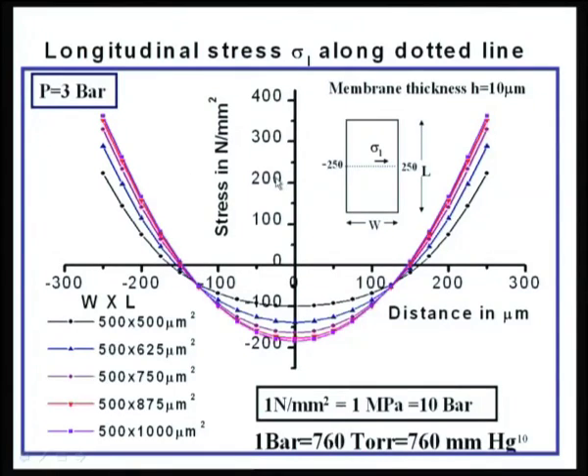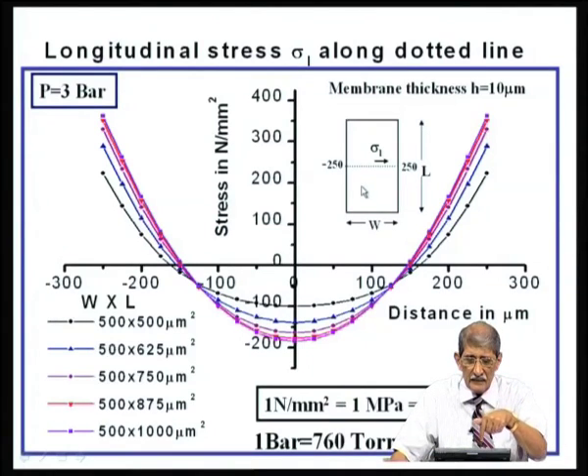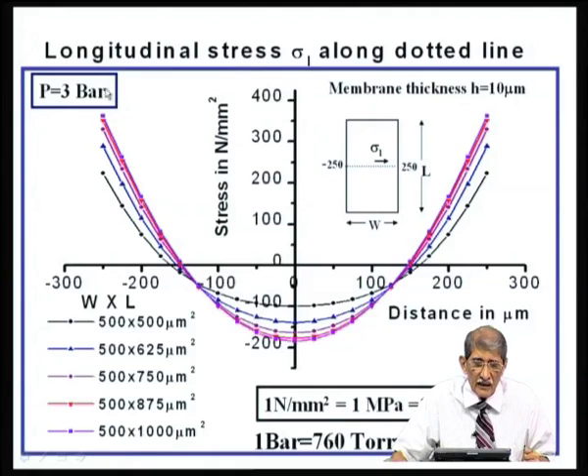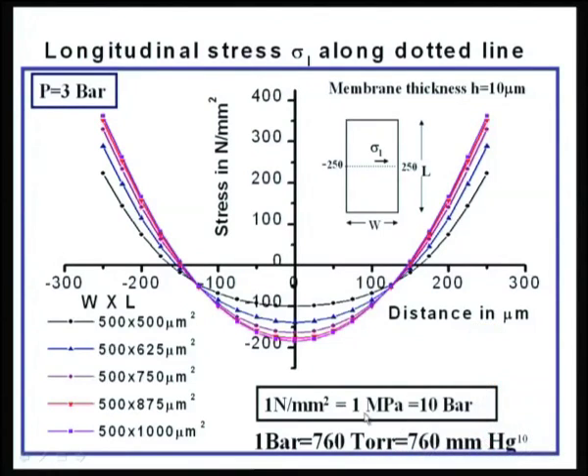At minus 250, the stress is 200 newtons per millimeter square, and 1 Newton per millimeter square is 10 bar, 10 atmospheres. So this is 2000 atmospheres. The membrane is subjected to a stress perpendicular to the plane of 3 atmospheres, 3 bar. 1 atmosphere is 1 bar, so 3 bar is 3 atmospheres. In fact, if you are familiar with other units for pressure, 1 bar is 760 torr, which is 760 millimeter of mercury, or 1 Newton per millimeter square is 1 megapascal.